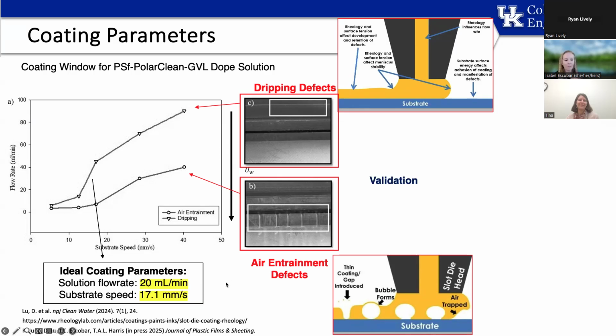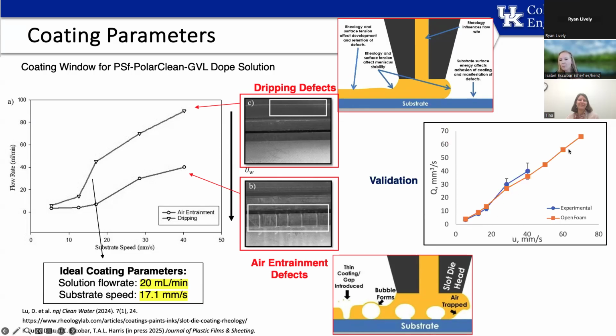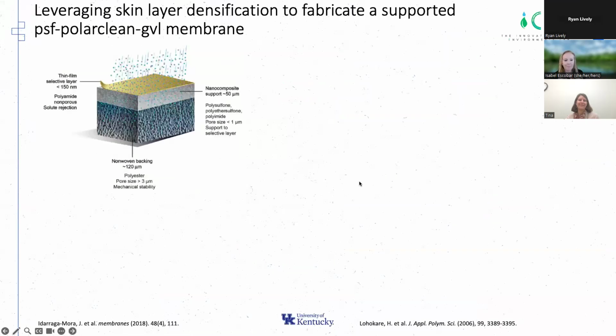And when we do it with the simulation, we were able to validate that simulation. So here, these are the experimental results. These are the OpenFOAM results that within the same range, they follow the same trend within the same standard error. And we were able to continue that casting window. So being able to use the validation, being able to use OpenFOAM shows that we can indeed simulate how the dope behaves within the slot die coater.